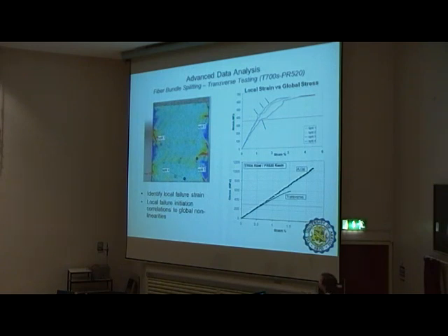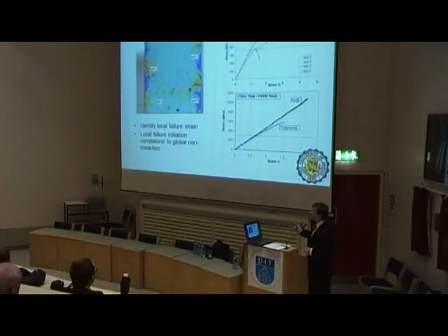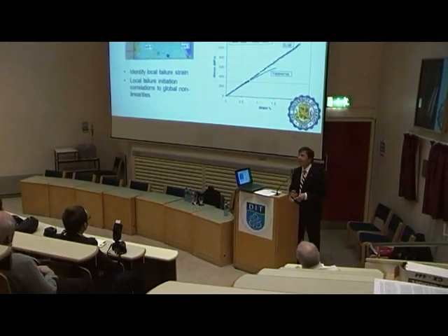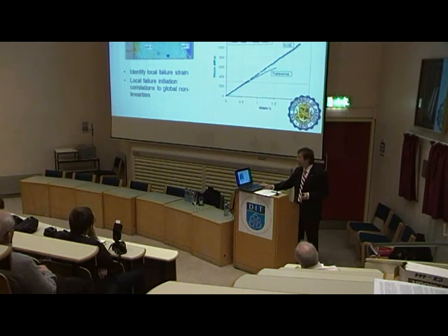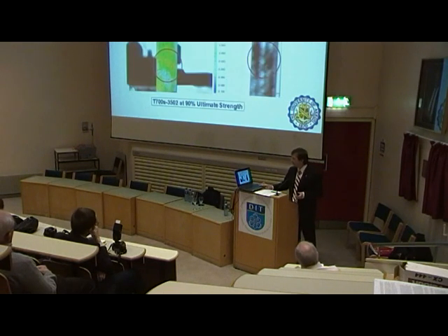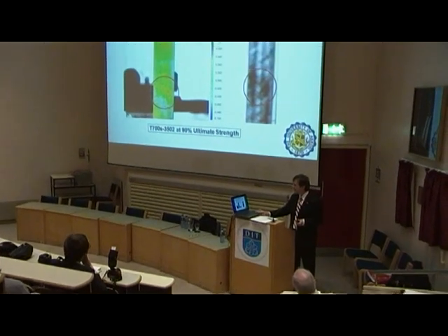This is an experiment where you can see the edge effect, which gives different stresses than inside, and of course non-homogeneous stresses or strains are visible, like maybe local damage, split or fracture or debonding between fiber and matrix. All of that can be overlapped on the global stress strain, but locally they produce a different stress strain relationship, and this needs to be known and somehow incorporated into the constitutive equation later in the modeling.